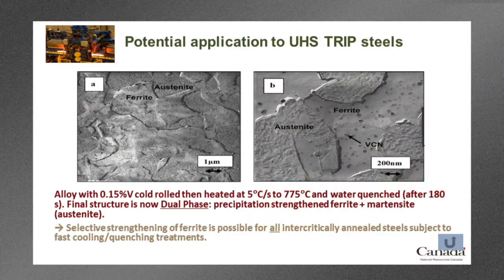The same technique can be applied to a different type of steels. These are called dual-phase steels, where we don't have any residual austenite. What we actually have is just ferrite and martensite. And this is an example of that, taken from using the trip steel chemistry. But what we did was we quenched it directly from the intercritical annealing temperature, and so we were in the ferrite austenite region. That gives you a two-phase final microstructure, which would be martensite and ferrite, a dual-phase microstructure.